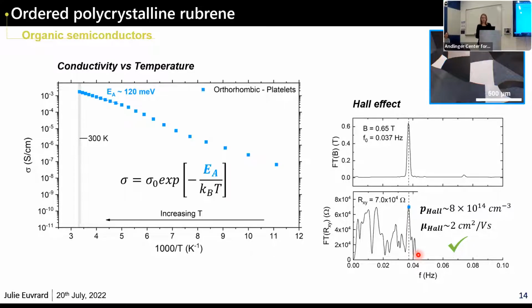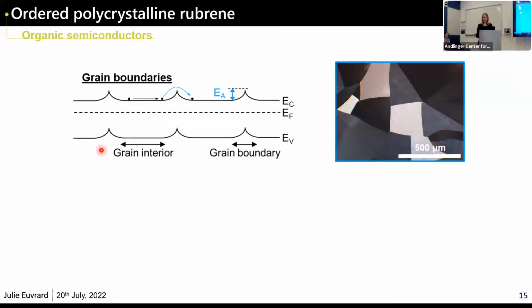What about conductivity? So here you have conductivity. Just pay attention to the x-axis. It's as a function of inverse temperature. So the highest temperature is actually on the left here. And what we obtain is the opposite of what we would expect for band-like, because the conductivity is increasing with temperature here. But it's not inconsistent with band-like, and I'll explain why.